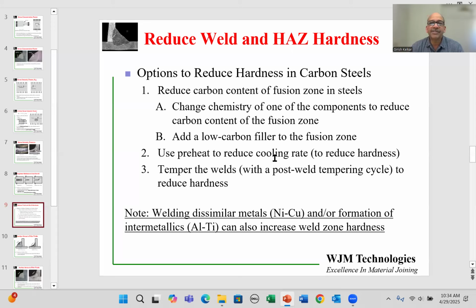Now, carbon in carbon steels is not the only reason why the welds can be hard. There are other reasons. For example, when you weld dissimilar metals such as nickel and copper, the weld itself does not have any reaction products, but it is actually very brittle. And sometimes we have, say, mixtures such as aluminum and titanium, which will actually react and form intermetallics, and these intermetallics are also very brittle. So anything that can lead to excessive brittleness in the weld will make your weld more susceptible to crack growth.